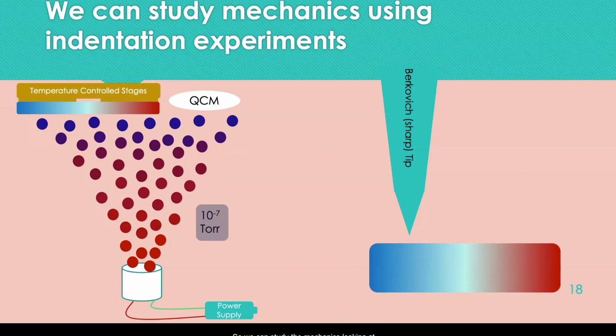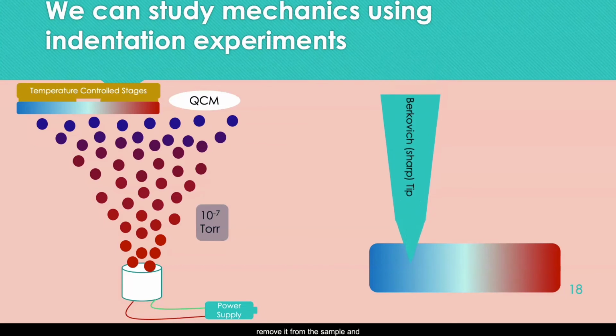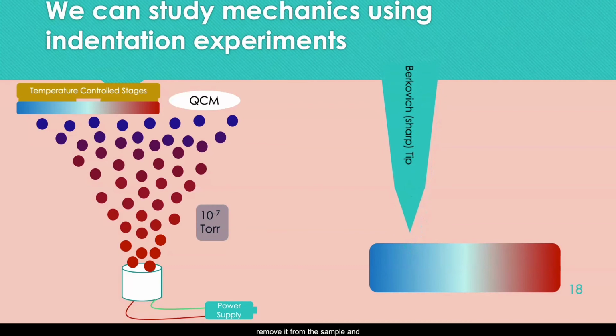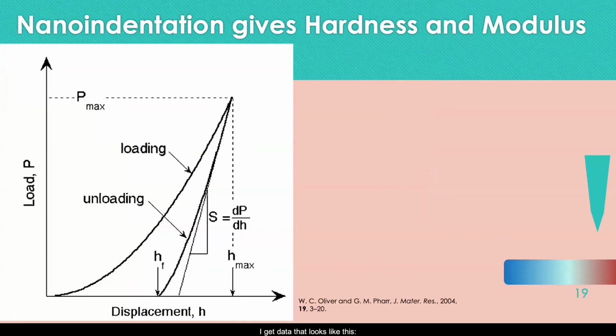So we can study the mechanics looking at specifically indentation experiments. In this, I take a sharp tip, load it onto the sample, remove it from the sample, and watch the recovery of the indentation during the removal to extract out mechanical properties. So to take a deeper dive into what this looks like, I get data that looks like this. I have the load applied versus the displacement of the tip from that applied load.